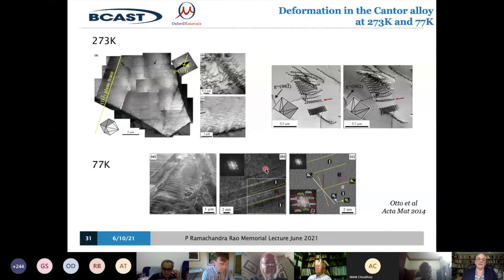The next property I want to mention in this context is the deformation behavior, the way that the material can elongate and be stretched. We've already talked about that a little bit, and the mechanism by which that happens, I said, was that planes of atoms roll over each other. But they do that, of course, as the material scientists know, via the action of something called dislocations. For the non-material scientists, you don't need to know what dislocations are. They're lines in the material. Each of these lines here is a dislocation, and this is a picture of these dislocations in one of the Cantor alloys. And these lines of disorganization move around the material, and they cause the planes to roll over each other and the material to deform.